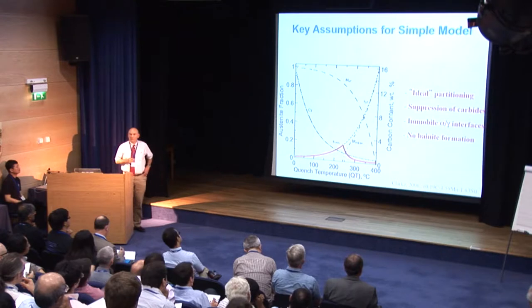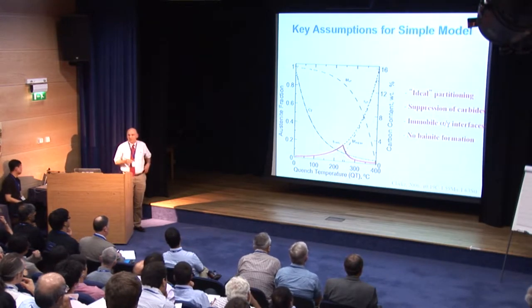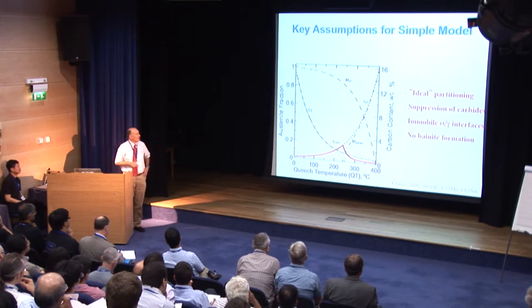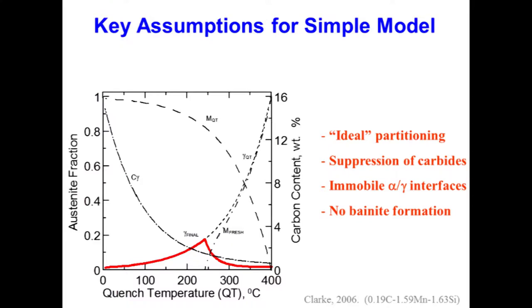Embedded in this fairly simple model were some assumptions that are pretty important from a physical metallurgy standpoint. First of all, that we had ideal partitioning, right? All the carbon would like to go into the austenite. That we've completely suppressed the precipitation of carbides or conventional tempering reactions. Once you form the martensite during quenching, that you don't change the phase fractions anymore. That is, that the interfaces are immobile. And that the austenite doesn't decompose in other ways, like bainite formation. So these assumptions are not always correct, and so they're the source of a lot of interesting follow-up that we can do as a metallurgical community. But still, the model is very helpful to guide us.